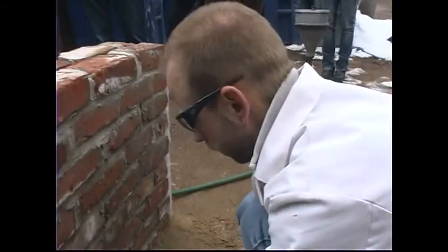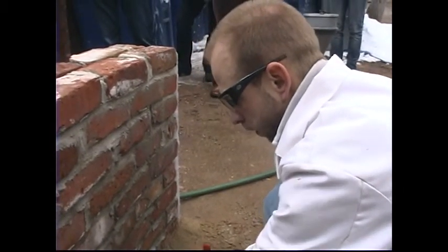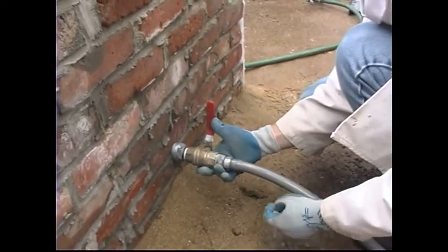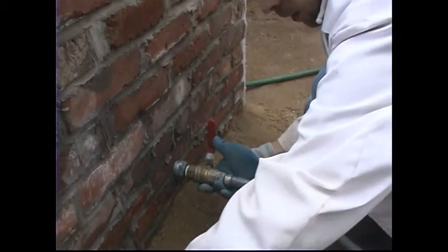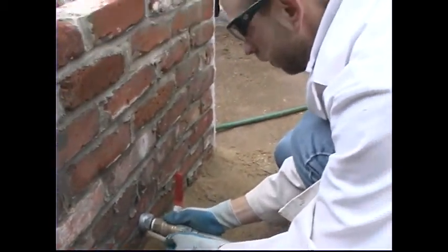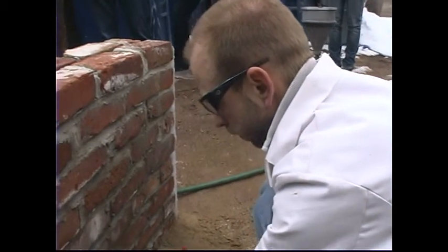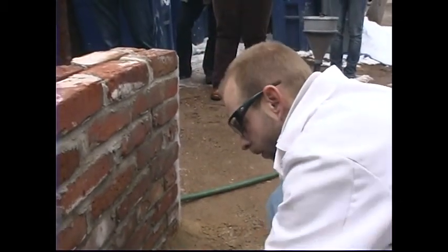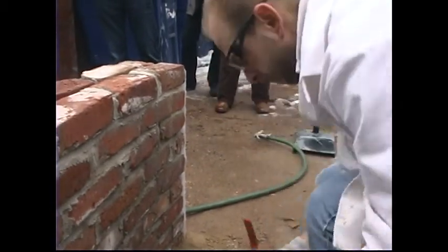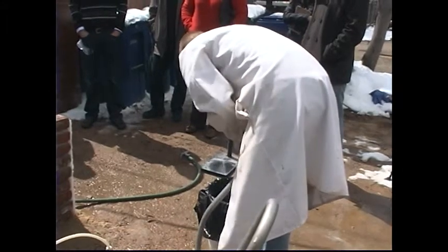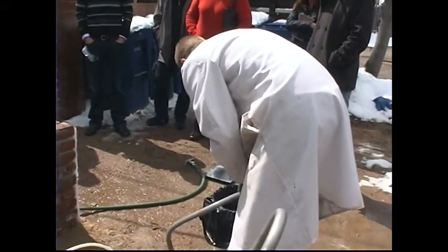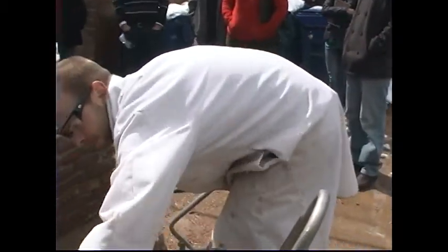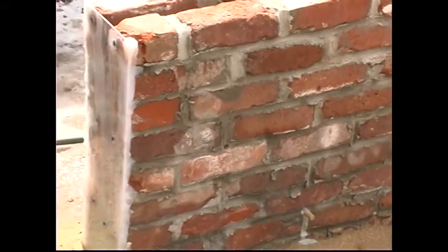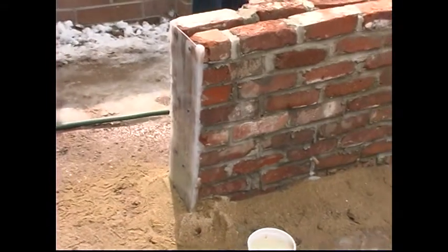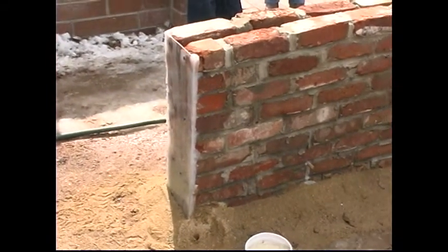For bigger projects, the crew will use a pressure pot for a crack injection because it's almost no material. It's like a couple quarts of material goes a long ways in a 1/16 of an inch crack. For bigger projects, like Missouri and all the work in New Orleans, they have silo systems where all the material is pre-blended, shipped down to the site in 3,000-pound bags. A silo feeds into an automatic mixer that automatically doses the water. There's not a bunch of guys with drills and 5-gallon buckets. It's really like industrial scale injection. They'll go through 3,000 pounds of material in about 2 days sometimes on some projects.